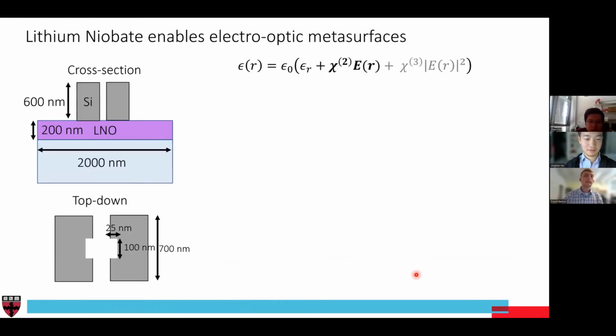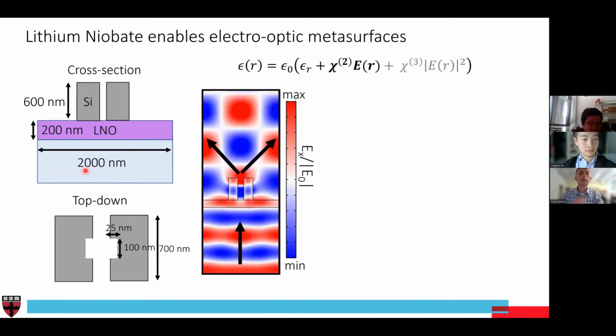So, what we did is to use the fact that lithium niobate can change its optical properties using this applied electric field. And we designed structures that give us dynamic and tunable responses. So here, we designed a structure that acts as a beam splitter. Light will come in from the bottom and will be redirected to propagate in both the plus 45 and minus 45 degrees, effectively splitting the light in two. And this is quite useful in a variety of different optical components,